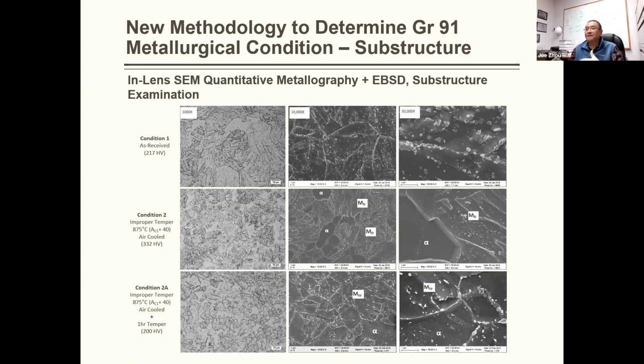So that is going to take a lot of creep testing, interrupted creep tests. Then we can stop that and see when you reach 20% life, this is the microstructure; at 50% life, this is the microstructure, to see how the microstructure is going to degrade in the service condition. So this needs a lot of groundwork to establish this pattern. Now we are just beginning to do this, but it's going to take a lot of time.